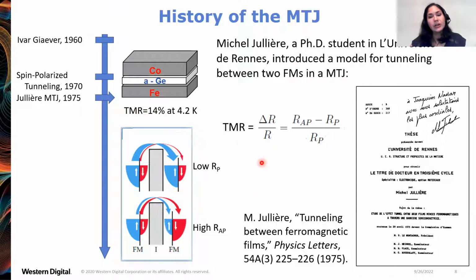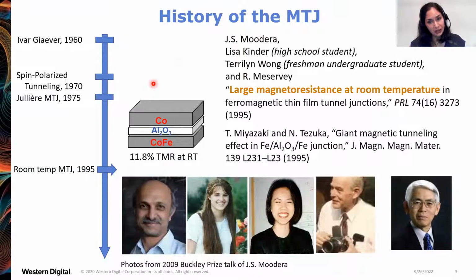And Jullière defined a tunnel magnetoresistance ratio as the difference between the anti-parallel and parallel state, or the high resistance and low resistance state, over the resistance of the parallel state. And for his thesis work, his tunnel junction using amorphous germanium tunnel barriers had a TMR ratio of 14%, just at low temperature, at liquid helium temperature. But when he did the experiment at room temperature, there was no TMR. And there was no TMR at room temperature until 20 years later.